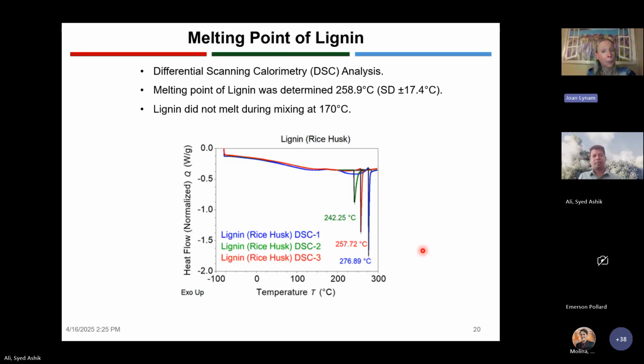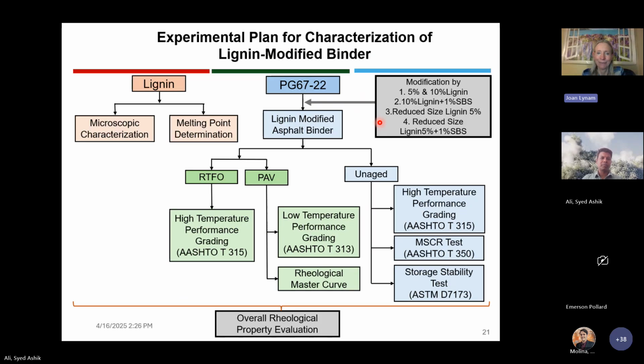And we also checked the melting point of lignin and found that it was around 260 degrees C. Those are 3 different runs when we did differential scanning calorimetry. And so basically, since the melting point is pretty high, it's not melting when we're mixing it into the binder at 170 degrees C. So pretty much it's staying as a particle, it's not melting. And we can go on to the next slide.